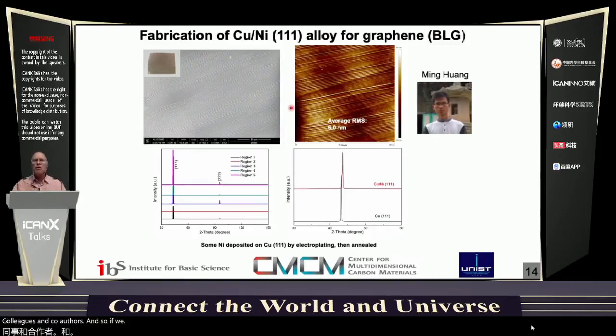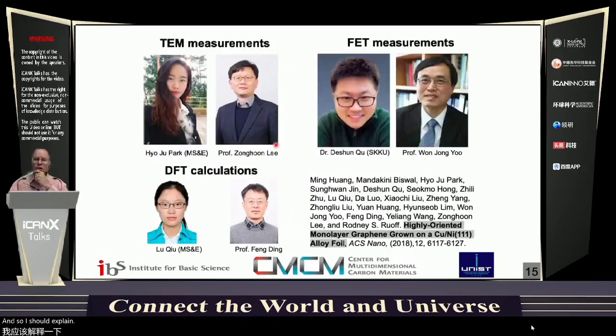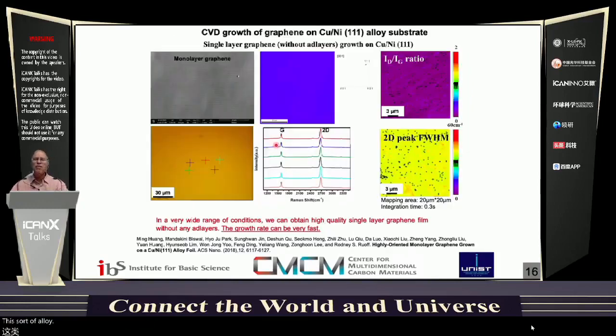And so if we use the 90-10, then we might get mostly single layer and bilayer, but those were polycrystalline at the time. So having single crystal and having only copper and nickel and controlling the amount of nickel allows us to potentially make multi-layer graphene with fine control. And so I should explain, this is showing this work on growth on this sort of alloy foil with a moderate or small amount of nickel present.